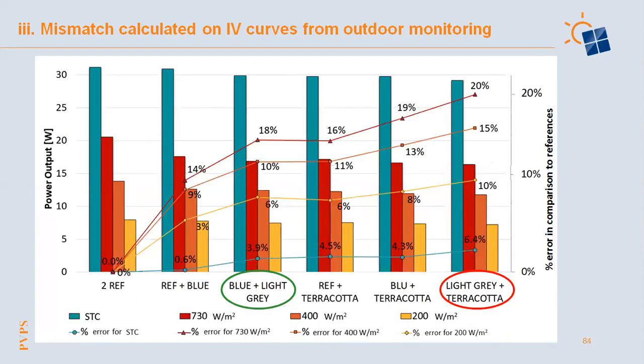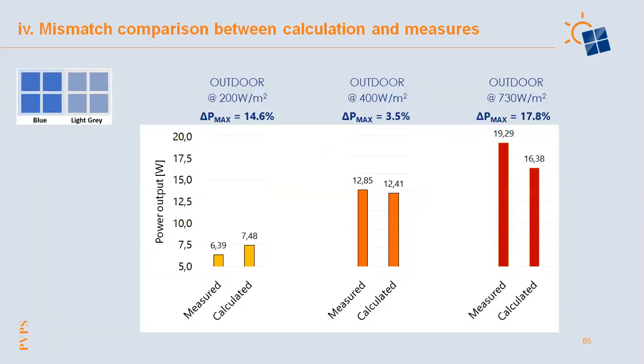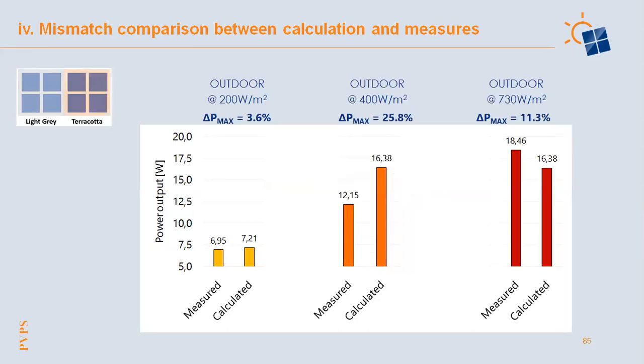But we were also interested in applying this method to outdoor conditions. In this graph, you can see the values of the power output for the different combinations of colored modules at indoor condition in green, but also in red, orange, and yellow, the calculated value of power for different combinations of modules when they are outdoor. So we merged the IV curves from outdoor monitoring, and we calculated the mismatch and the power output. You can see that the power reduction in this case is significantly higher, even if the trend is more or less the same. Then, to evaluate this calculation, we connected in series different combinations of modules, and we measured the real value, which is lower than the one calculated, and we have huge differences.